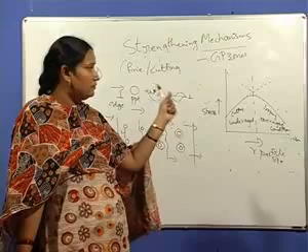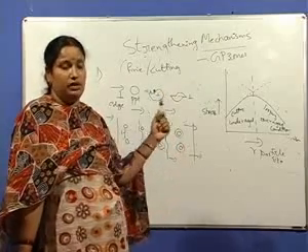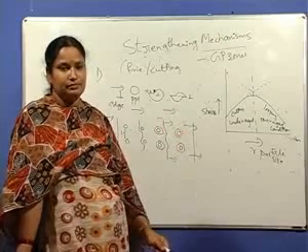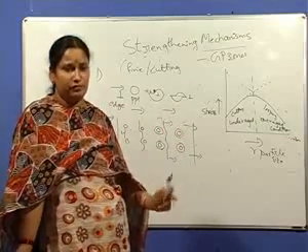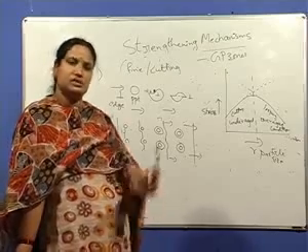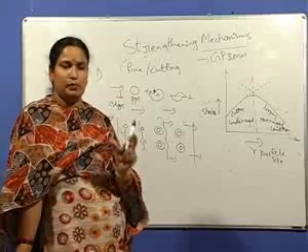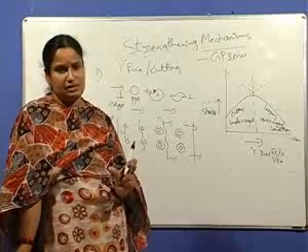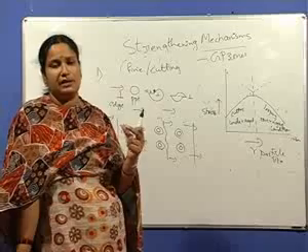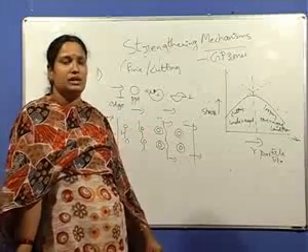For the aluminum copper alloy system, we have seen various transition phases that may not be found in all precipitation hardenable alloys. But one thing that is found in all precipitation hardenable alloy systems is the formation of a coherent precipitate phase, and with still further increase in time, the coherency is lost and precipitate coarsening takes place.